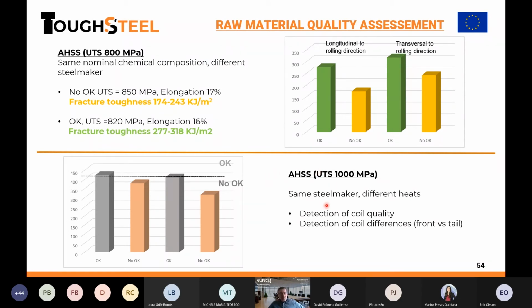Another example. This is the same steel maker, but different heats. We get materials that are OK and not OK. Again, the same tensile properties, but the toughness in the OK ones was always higher than in the not-OK ones. So this is nice. How can we measure it in the lab? Laura Griffin, after the coffee break, will explain how to effectively measure this. It is a simple method to obtain it. We evolved from a complex lab test for fracture to a very simple lab test. I think you will like this approach because it's absolutely applicable, straightforward, and applicable to material quality assessment in a production line.